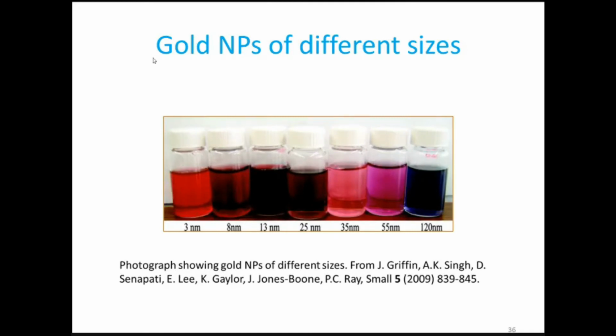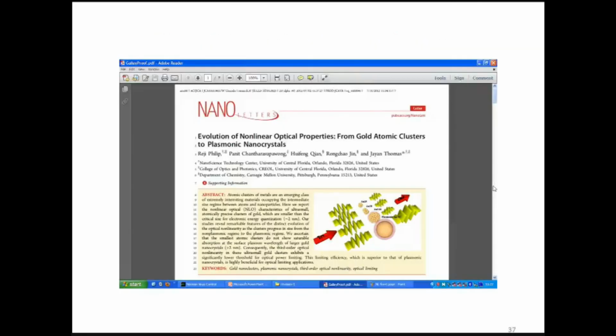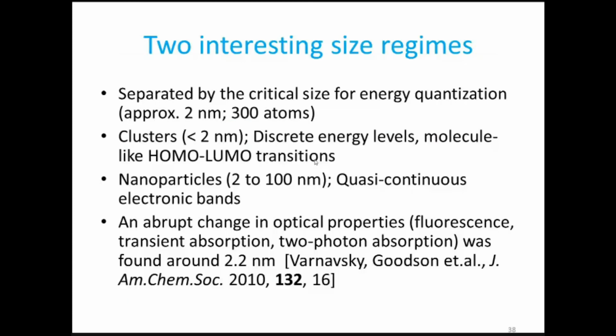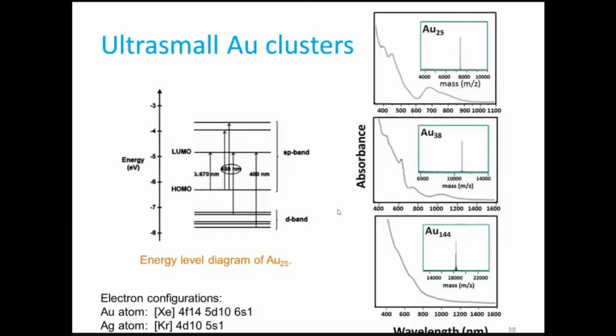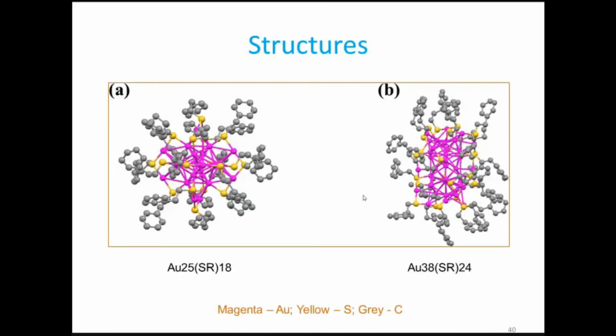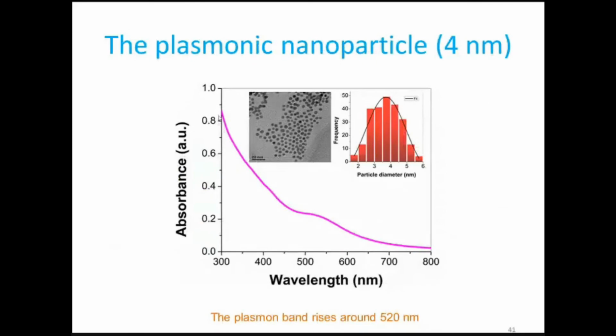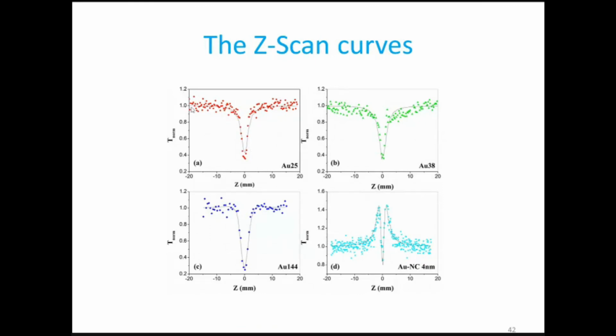Okay. So gold nanoparticles of different sizes we investigated. This is the paper that appeared later in Nano Letters, Evolution of Nonlinear Optical Properties from Gold Atomic Clusters to Plasmonic Nanocrystals. So basically we tried different sizes of gold nanoparticles, and when you go to very small gold clusters, you can see that they start behaving like molecules actually. Unfortunately, I cannot go into any of the details now. And we compared the behavior of plasmonic nanoparticles of 4 nanometer size. And we measured the Z-scans.